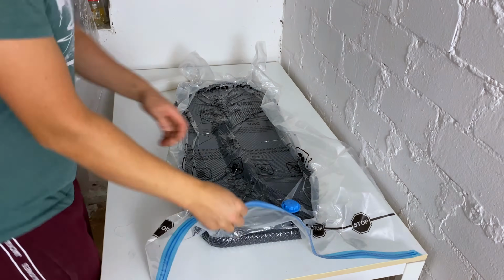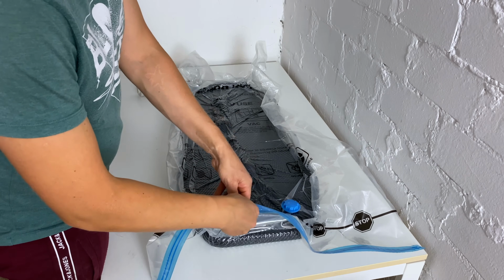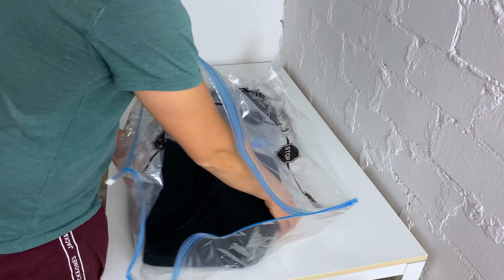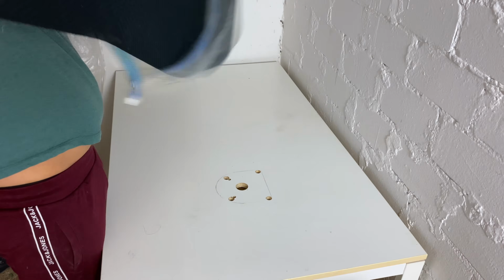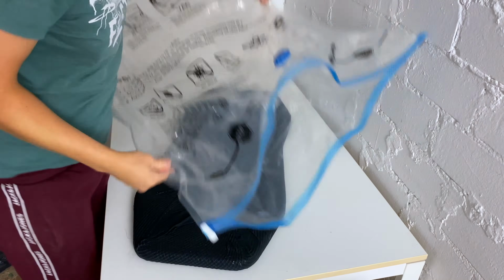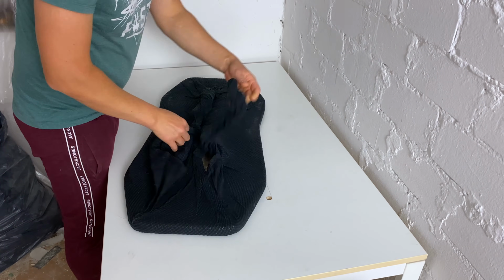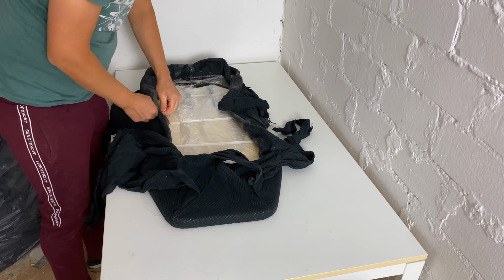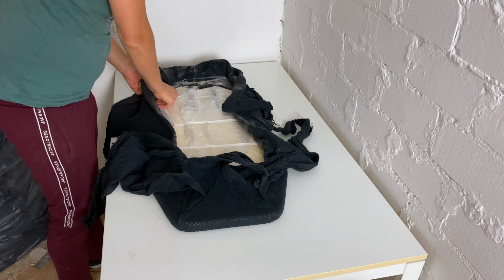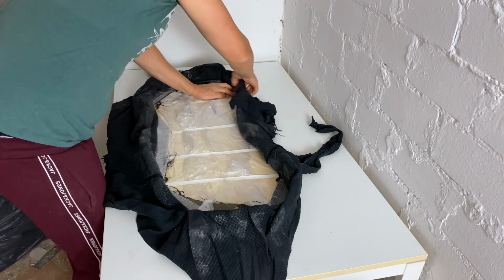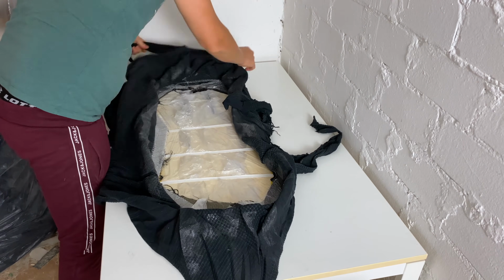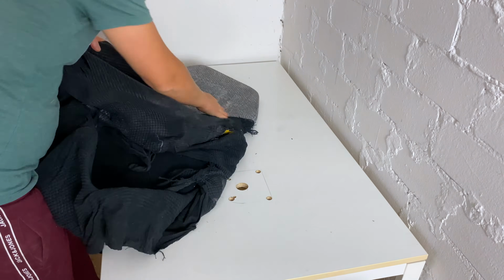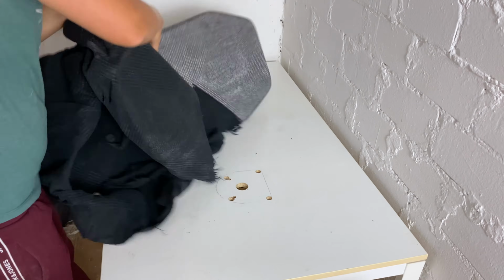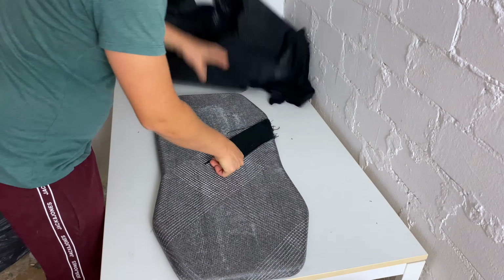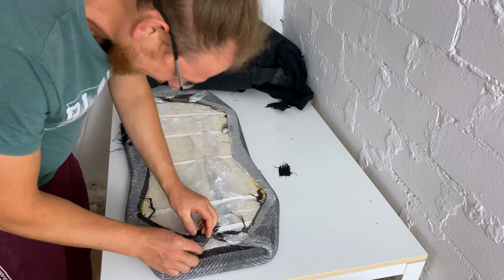After the epoxy has cured, I unwrap the board, removing the blanket and peel ply. This was the first time I had worked with carbon fiber. The resulting carbon composite is much harder and more stable than glass fiber composites. This is where I realized that I could have done without the 3 layers of glass fiber, because the 1 layer of carbon is already very stable and stiff.